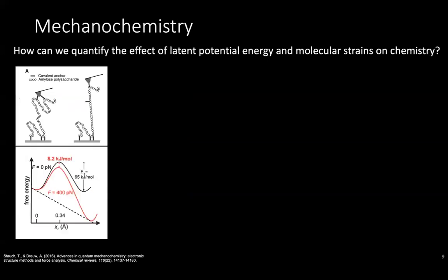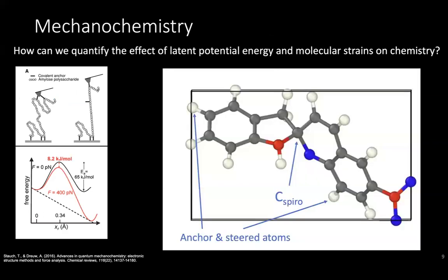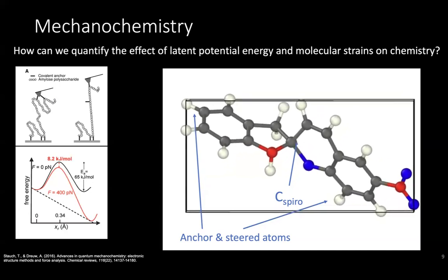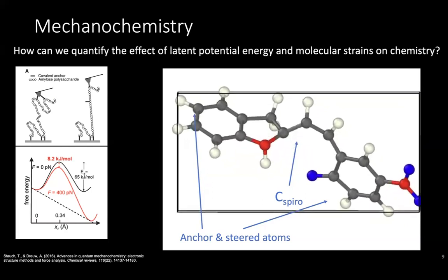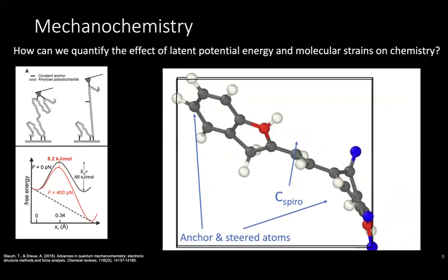So this is mechanochemistry. And of course, we didn't invent mechanochemistry. Mechanochemistry is known. And I'll show you an example, right? So if you take a molecule, you pull from it, you break it. We can understand that by having an external force. It basically changes the energy landscape that your reaction lives around. This is an example of a mechanophore. So we're pulling on this molecule and we're going to break this spiro bond, and these molecules change color when they break the bond, okay? So this is the type of mechanochemistry that people have characterized. It's two-body elongation type mechanochemistry. But if you remember our molecules, we're not elongating, this is a shock. So it's many-body distortions that add to the latent space.